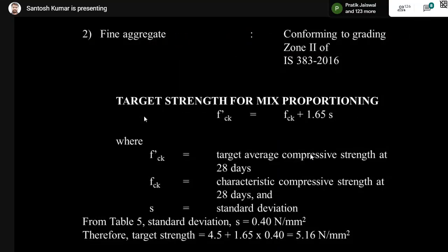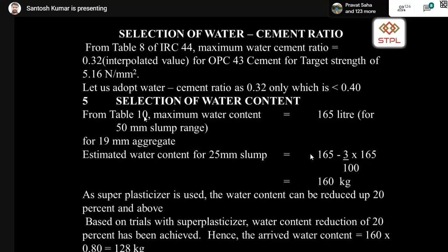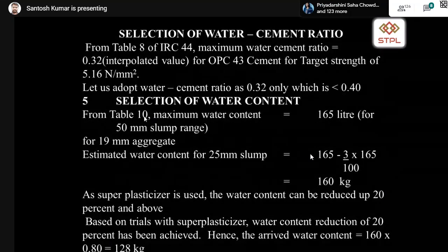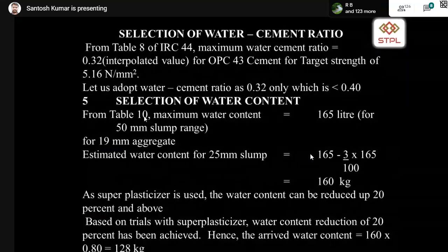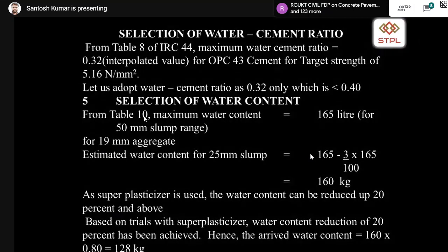So you can see the target mean strength for M40 grade of concrete in terms of compressive strength will be 5.16 Newton per mm square. So again, in this case, you have to reduce the water by 3%. So here what we have taken is the water cement ratio 0.32, and the slump value is designed for 50 mm in the table, but in our mix design it is designed for 25 mm. So we have to reduce by 3% water.